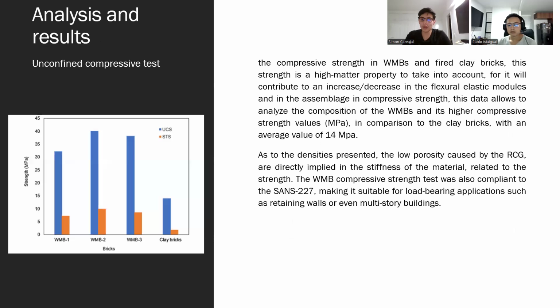So now we're going to analyze the results, starting with the unconfined compressive strength. As you can see in the graph at the left of me, WMB has an average value of 35 MPa, and the clay bricks show an average value of 14 MPa.